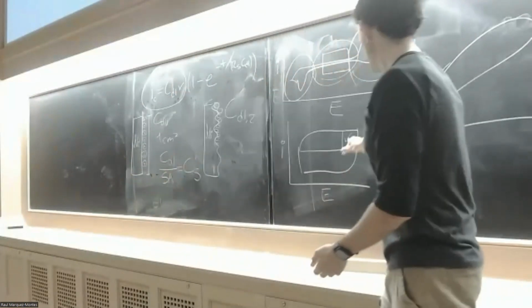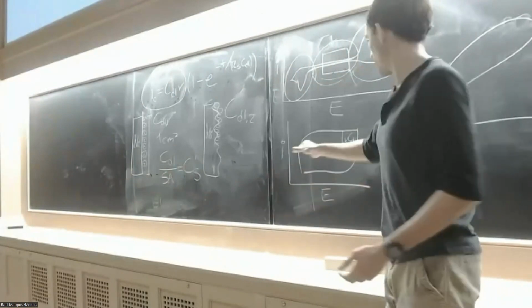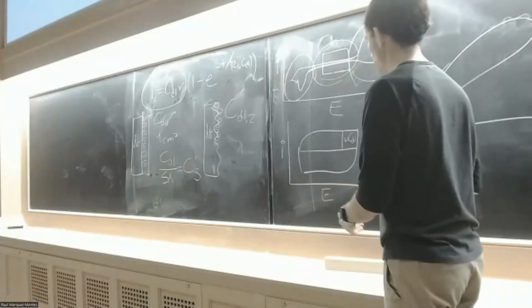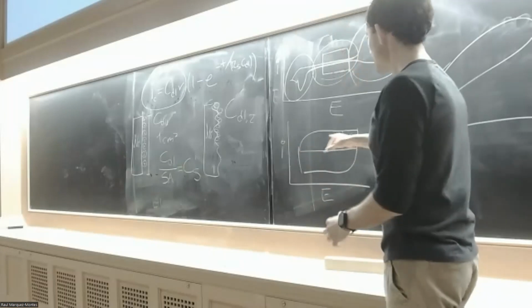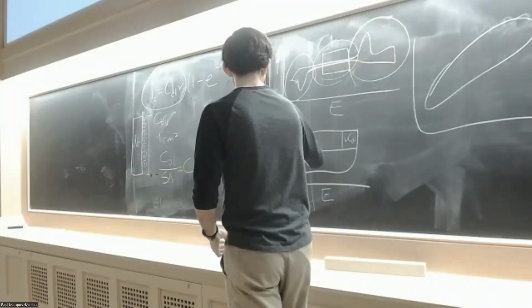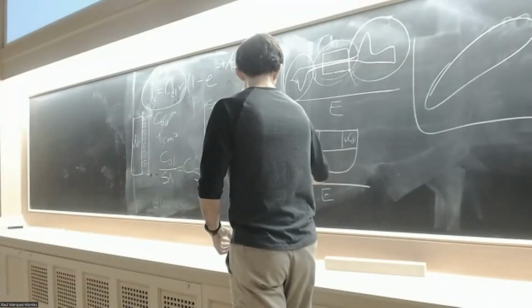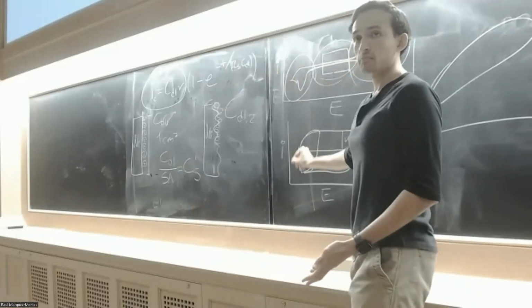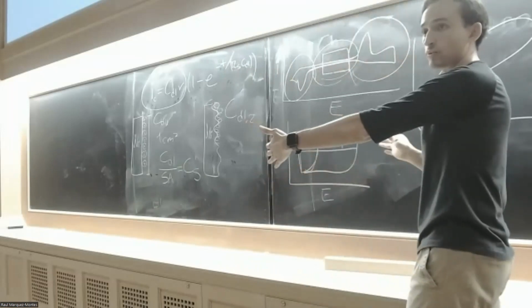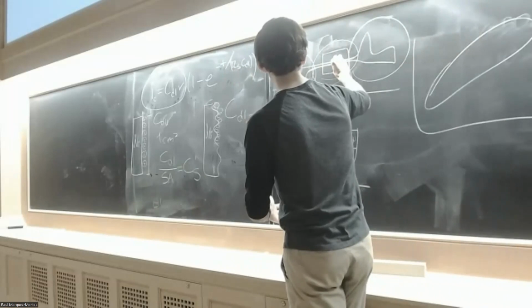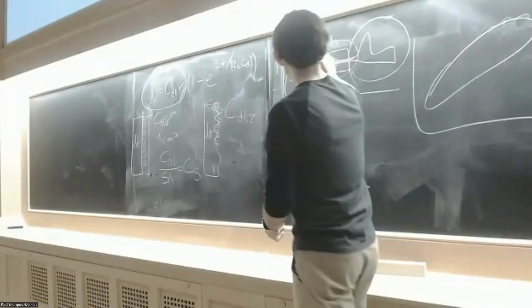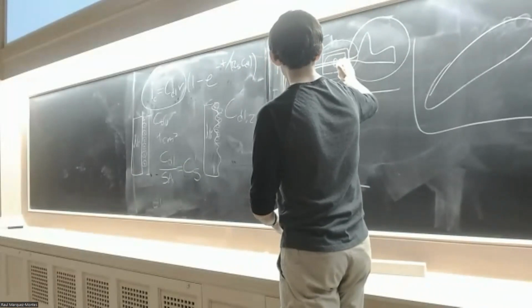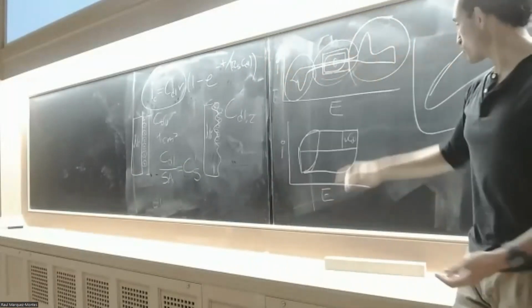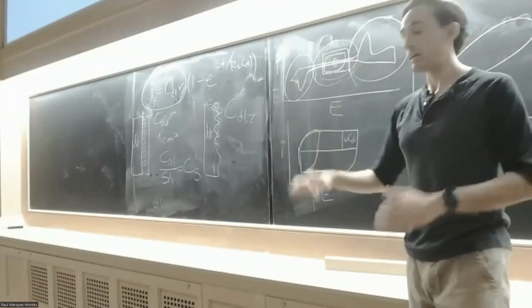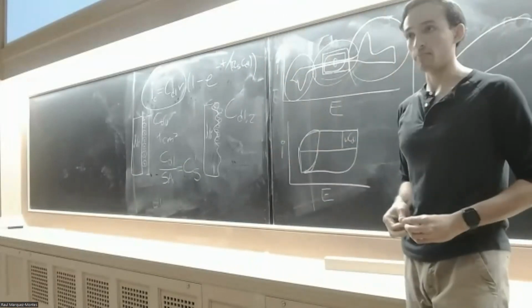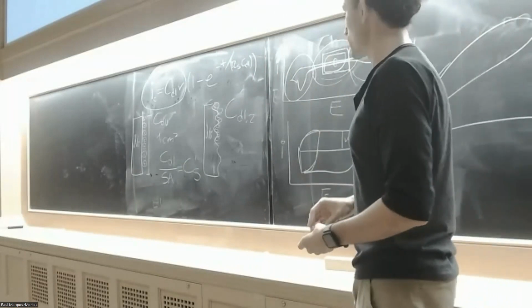And experimentally, it is just by looking at the shape of this potential window or these potentials. So for instance, if you do your analysis just here, you're unable to see this plateau. So you need to extend the potential window. In this scenario here, instead of just running it here, you should increase the potential window like this. So you are able to get this plateau, and you are able to get this term there. Okay, so this is the third consideration.